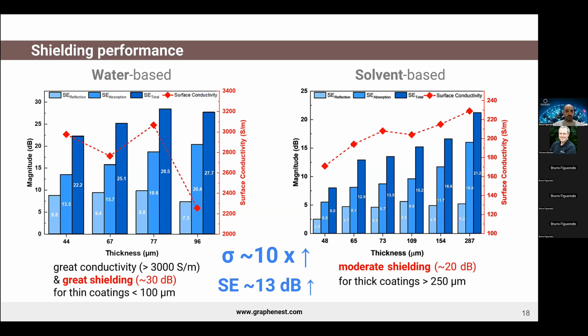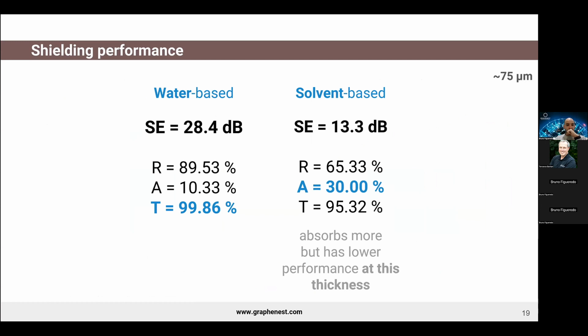Well, the great advantage of the solvent-based solution is the fact that it allows producing thick coatings of around 300 micrometers. And not only that, because you will see that the solvent-based also has an opportunity when we are in need of having more absorption than reflection. And that's what the next slide is about.